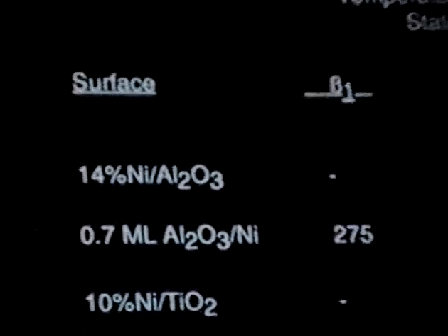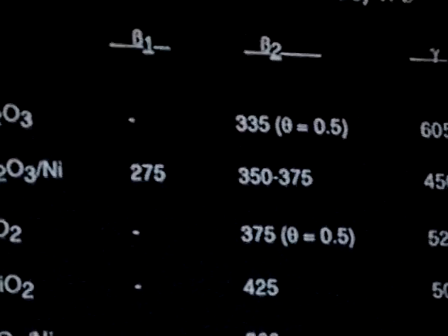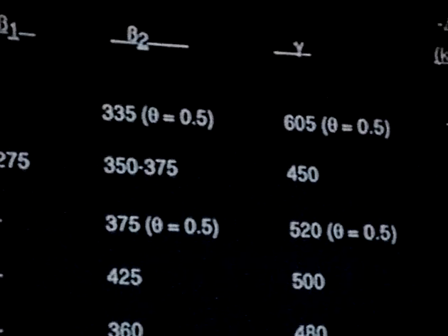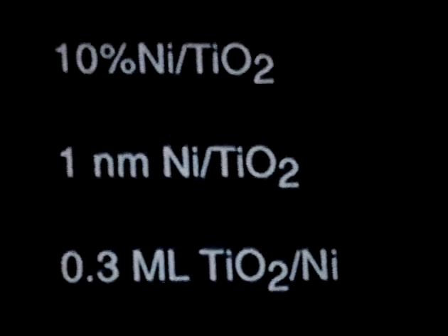The data are summarized here. In the case of both nickel-alumina and nickel-titania, you get lower and higher binding energies for the low and high-temperature states than the value of 90 to 96 kilojoules per mole observed with nickel-silica. The observation of these different binding states has a profound effect on the adsorption properties, the stoichiometries of adsorption, and also on the catalysis.